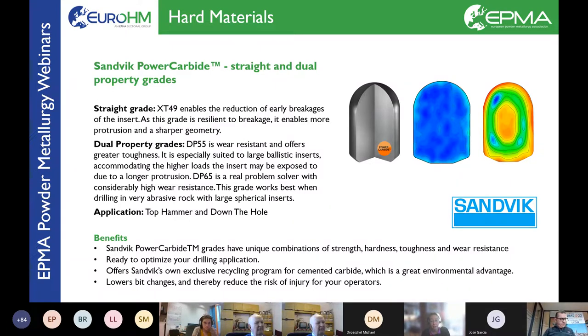This rock drilling grade is mainly used in the down the hole application, where the hammer is very close to the bit. So the impact of the hammer on the carbide is much more severe. And then you need this specially designed carbide to take the loads from the impact. Both of these grades belong to something called the Sandvik power carbide, and you can Google that and you could see all the different grades.